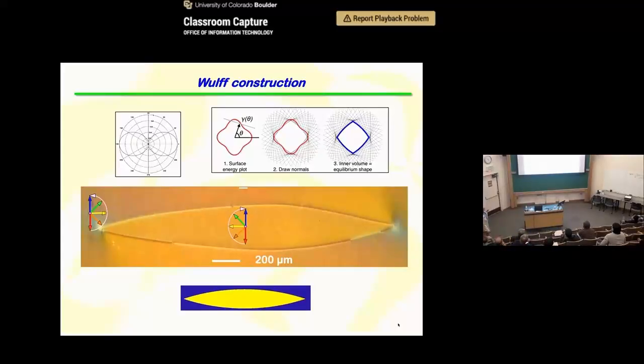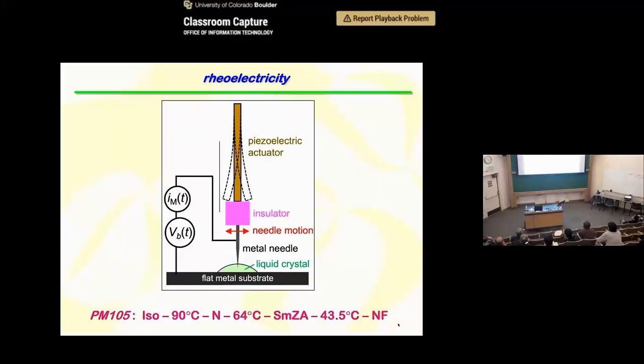So if you have a vertical wall, then in the middle of the cell, these two yellow arrows end up pointing in toward each other. That's space charge. But if you have a horizontal wall, then they sort of pass each other by. So a domain between these two textures will be extended to reduce space charge.